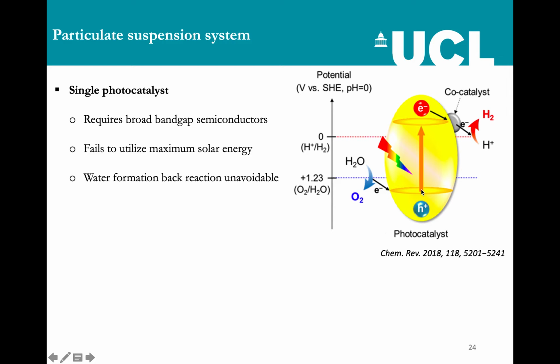and in order to perform reduction and oxidation, H2O to O2 is the oxidation and proton to hydrogen is the reduction reaction, we have to have both half reactions simultaneously. Otherwise, for example, if my material has a band gap which can perform only the reduction reaction but not the oxidation reaction, the holes we generate in the valence band corrode the photocatalyst material, so photocorrosion can happen. If we harvest these holes for the oxidation reaction, the photocorrosion can be avoided. That is why we have to have these two half reactions, oxidation and reduction, simultaneously.